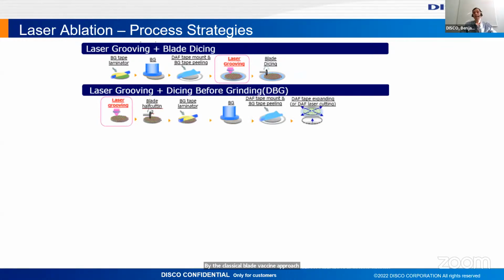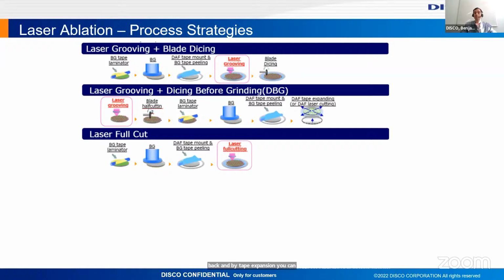Very similar, but a little bit changed in the sequence, is the dicing before grinding approach. Here you do the laser grooving and the blade half cut, still in thick wafer condition, and then you grind it back, and by tape expansion, you can release the chips into the individual dies. The third one is the laser full cut. The idea is obvious. You completely cut the wafer with the laser. You focus on your top side and remove material until you finally cut through.